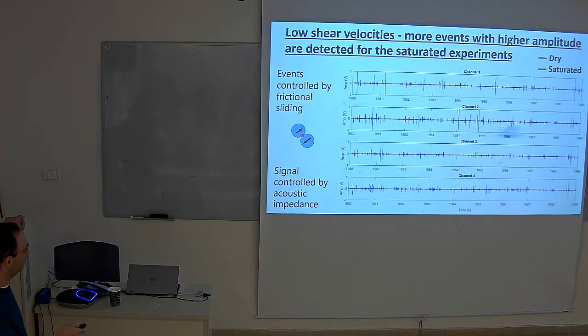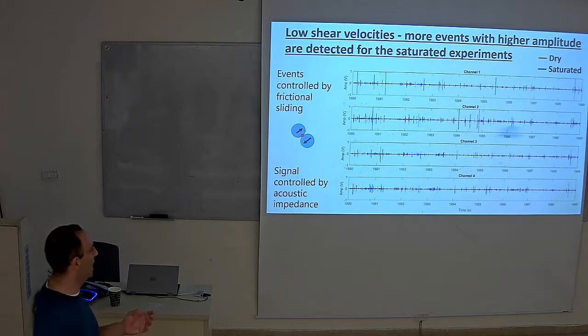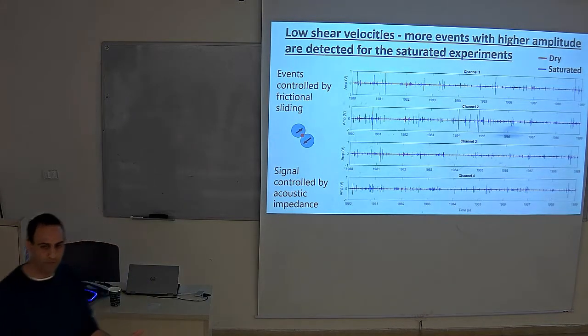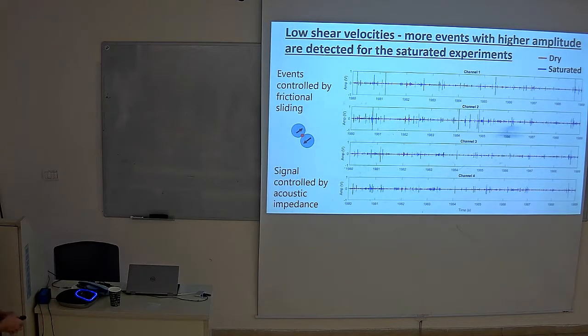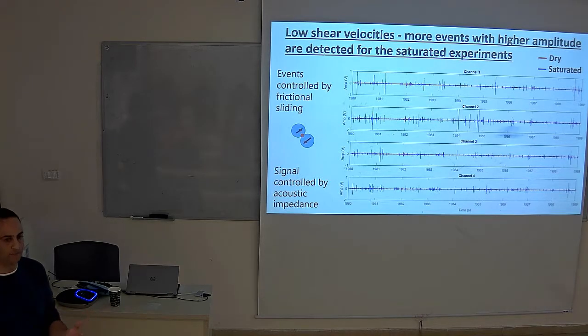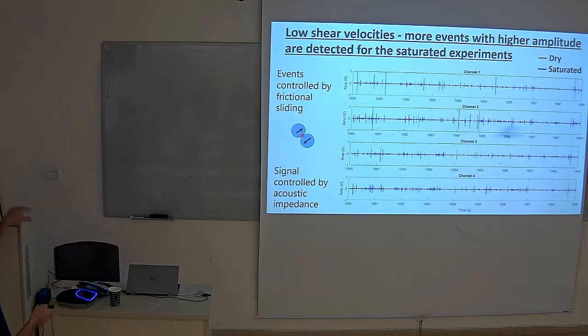And what can be easily seen is that the amplitude and the number of events is much higher for the water saturated experiment. And the question was if it's indeed a different source mechanism, or something else. So looking carefully at it, we suggested that it's acoustic impedance. It's actually causing the difference, which means that less energy is moving between the granular flow and the glass jacket where we put our sensors, and therefore we are getting less acoustic energy for the dry.